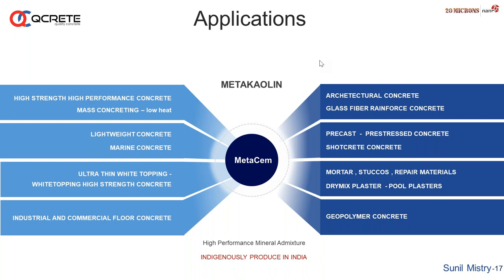It is also always advisable to use it with lightweight concrete and marine concrete, due to the chloride and permeability reduction possible here. So marine concrete is always advisable here. Many other concretes I mentioned. Lastly, geopolymer is coming up, and we have seen that addition of 5 to 7% of metakaolin gives excellent results in geopolymer concrete. And there are mortars also, grouts also. Everywhere metakaolin is suitable for various concrete applications.